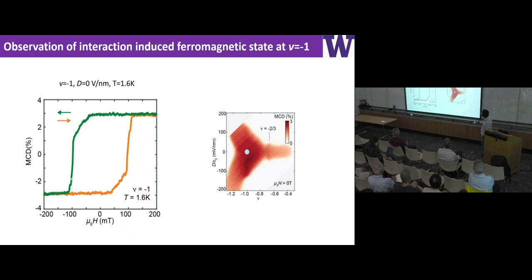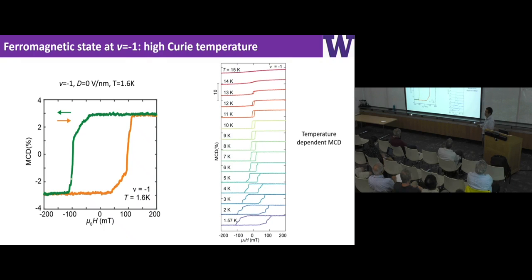I pick a spot in the phase space at the integer filling. Then we can perform these MCD measurements as a function of magnetic field. You can see this hysteresis loop, right? As I already told you, it is a hallmark of ferromagnetism. We can also measure the MCD as a function of temperature, and you can see the hysteresis vanishes as we raise the temperature. So the Curie temperature of the system is about 14 kelvin. It looks not too high, right? It's a low temperature, but actually, if you think about it, it's really high, because my Moiré unit cell has a wavelength of about 5 nanometers, and the filling factor is 1, meaning there's 1 carrier in every 5 nanometer unit cell.